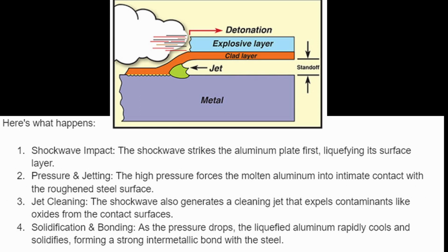This is what happens. 1. Shock wave impact. The shock wave strikes the aluminium plate first, liquefying its surface layer. 2. Pressure and jetting. The high pressure forces the molten aluminium into intimate contact with the roughened steel surface. 3. Jet cleaning. The shock wave also generates a cleaning jet that expels contaminants like oxides from the contact surfaces. 4. Solidification and bonding. As the pressure drops, the liquefied aluminium rapidly cools and solidifies, forming a strong intermetallic bond with the steel.